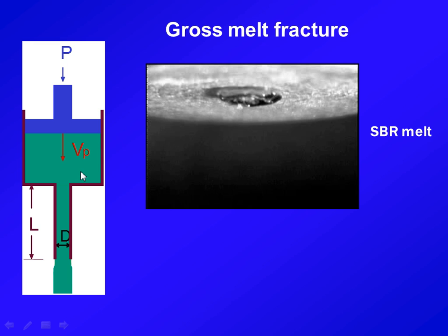So here's what you do. You get hold of a rheometer. You push your material into the die, which means the material has to be squeezed from the barrel into the die. And then you sit there and wait, doing nothing, until this sample already forgot it went through some dramatic history coming in, every molecule all relaxed, and then you start your experiment. And that's this movie.